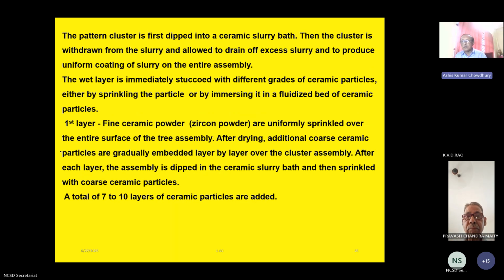The pattern cluster is first dipped into the ceramic slurry bath, then the cluster is withdrawn from the slurry and allowed to drain out the excess slurry, to produce a uniform coating of the slurry on the surface of the entire assembly. The wet layer is immediately coated with a different grade of ceramic particle, either by sprinkling the particle or by immersing it in a fluidized bed of ceramic particle. For the first layer, fine ceramic powder, that is zircon powder, is uniformly sprinkled over the entire surface